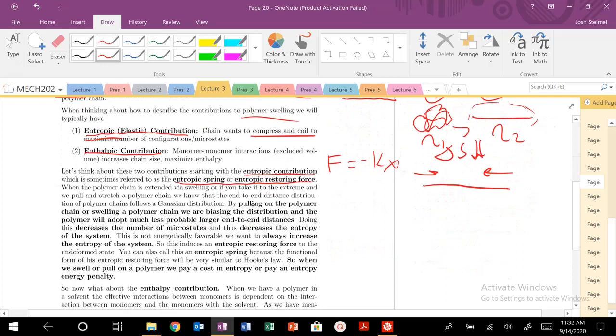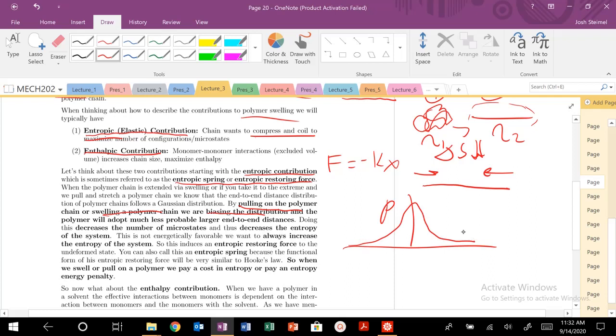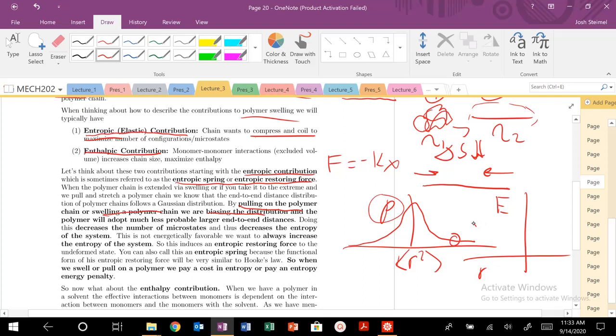When we pull on the polymer or the polymer swells, we are biasing our distribution. Remember back to our probability distributions — we want to be centered around the mean. But when we swell, we're forcing it into an unfavorable configuration at high R, which is low probability. If we look at the energetic state as a function of R, it's going to be very high energy — much less probable than the coiled state. So when we swell, we decrease the number of microstates, decrease entropy, and that is not good. It will want to restore and spring back into its coiled configuration.